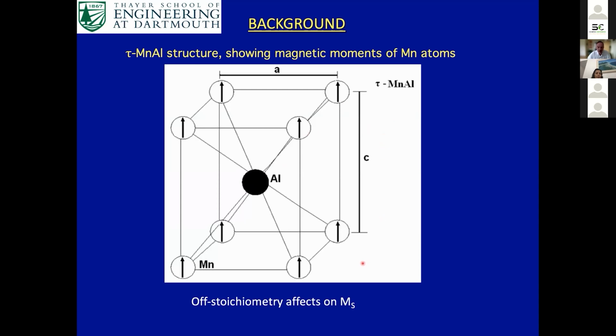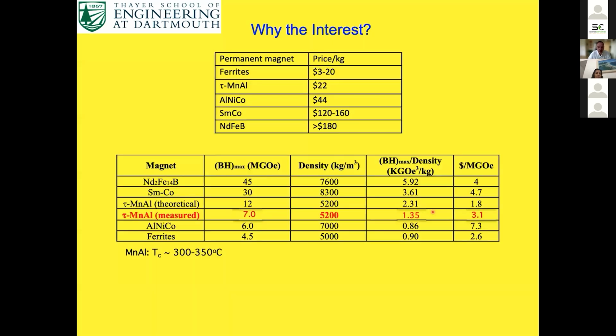One thing is the manganese aluminum exists over a range of compositions, and if you're manganese rich, then the excess manganese, of course, sits on the aluminum sites, and those atoms will line up with magnetic moments that are anti-parallel, so reduce the saturation magnetization.